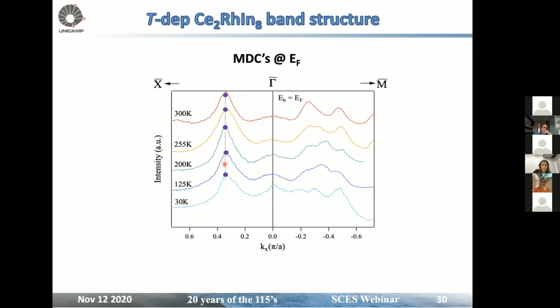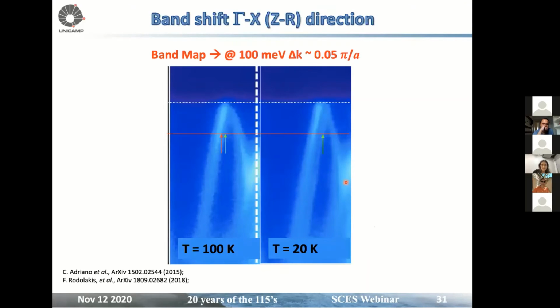So we have a big bright band here that doesn't move at all. And we have a shoulder here that is moving, oops, sorry, toward higher values of k. And that we can see if I zoom in, in very specific experiments like circular polarization and everything. So that band here is moving and shifting, but the shift is very small, at 100 meV, it's about that size.